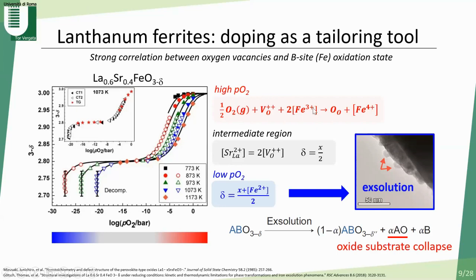at high oxygen partial pressure, we have almost no oxygen vacancies because they are compensated by iron 4+. In the intermediate region, by reduction of iron, the stoichiometry is 1/2 the doping of the A site, and at low pO2, the oxygen stoichiometry still increases up to exsolution of metallic iron in this case, and the oxide structure collapses.